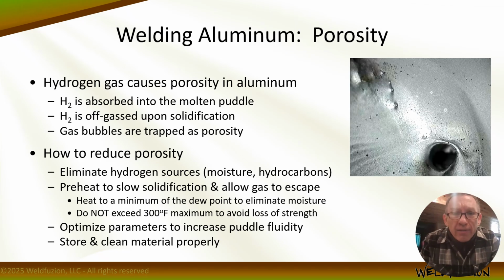So we have to be careful not to preheat too much and get into that aging temperature, or we could be doing detrimental damage to the mechanical properties of the base metal. For that reason, we recommend 250 degree preheat maximum. It gets rid of the moisture, it slows the solidification rate, and is not significant enough to change the mechanical properties of the base material.